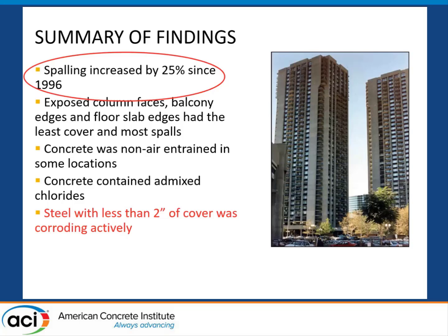So by the time they did the job in 2003, there were over 10,000 spalls between the two buildings, okay? And that number was just getting worse. So I think the owner realized they could not really put this off any longer. And again, this issue with the concrete cover and the active corrosion. So they had really corrosion throughout.